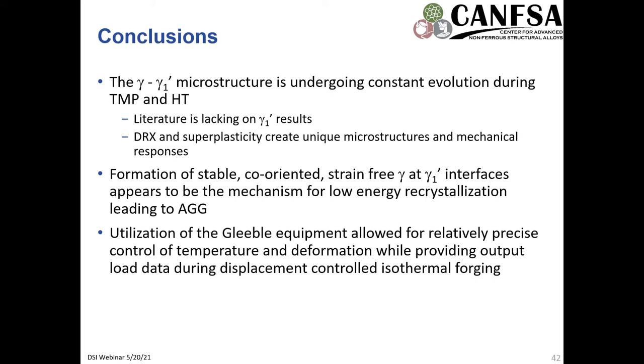And these eventually grow to be very large grains that self-impinge upon each other once all of the stored energy has been consumed, and you have very few large gamma grains with low amounts of grain boundary energy or stored energy in the form of dislocation density left in the material. And by utilizing the Gleeble equipment, we've had relatively precise control of temperature and the deformation steps while providing output load data during displacement-controlled isothermal forging. This has been really helpful for understanding the mechanical response of the material during these isothermal forging steps.